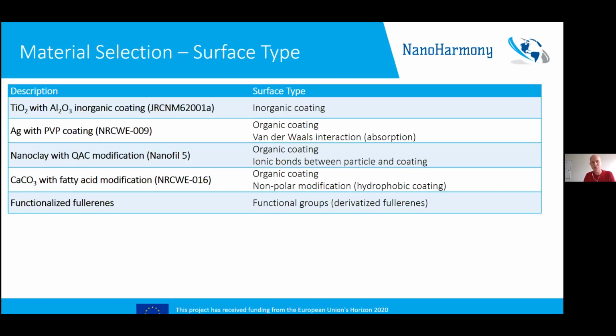And these 5 compounds were a titanium compound with both inorganic and organic surface coating, a silver compound with a PVP polymer coating, a modified clay and nanoclay, which was partly ion exchanged with quaternary ammonium compounds, and a calcium carbonate core with fatty acid modification, and finally a fullerene, which was covalently functionalized with side groups to separate it from typical fullerenes. So with this choice, we use different types of coatings and bonding type.